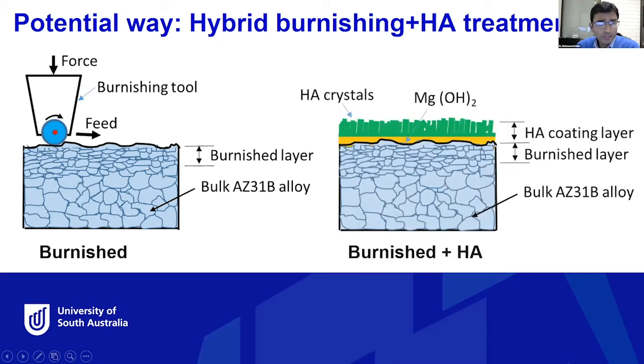And then we said, okay, after we do the burnishing, why not apply a coating, which could not only add another layer of corrosion barrier, but also give more benefit in terms of osteointegration. So hydroxyapatite is another compound we can consider here, and we can deposit that hydroxyapatite on top of the mechanically modified or burnished surface. Hydroxyapatite can provide two things: one is an additional corrosion barrier, and the other is helping bone to grow around the implant.